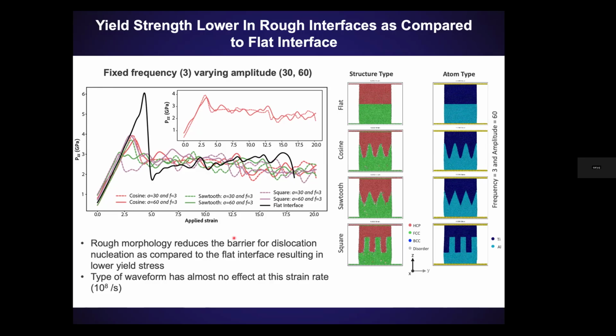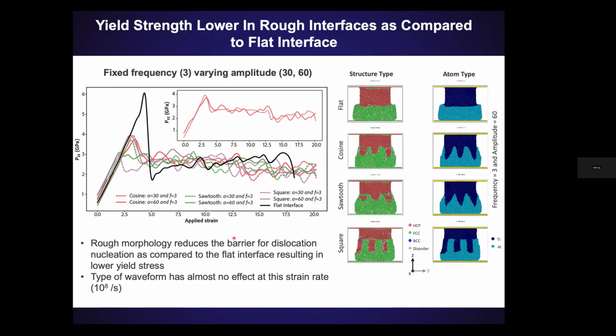So I'm playing a movie on the right side. In the movie on this side, the atoms are colored by structure. So green is FCC, red is HCP, blue is BCC, and then gray is just disordered, we don't know what it is. And here it's colored by atom type, titanium and aluminum. The first thing you'll notice is that aluminum is much softer than titanium. So when you're compressing the material, you are getting a mushrooming effect around the titanium. That makes total sense. The other thing is when you go from the flat to these different shape interfaces, you see these lines that are forming here. They're stacking faults, essentially left behind by dislocations that are nucleating at these rough regions of the interface. You don't see them in the flat interface.